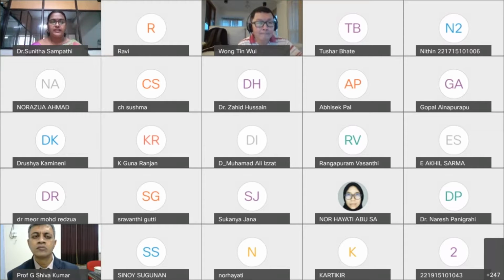Yes, you're absolutely right. Whatever nano suspensions we kept for the stability, we did not freeze dry. In fact, we kept them in the form of a suspension itself at the different conditions. That is the first thing. The second thing is maybe it could be related to Ostwald ripening. Maybe the stabilizers we were using, especially the HPMC, are leading to Ostwald ripening. That could be one of the reasons for the increase in particle size.